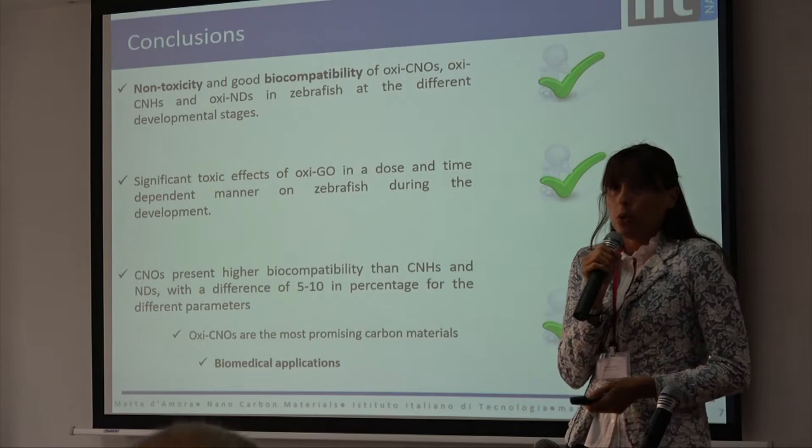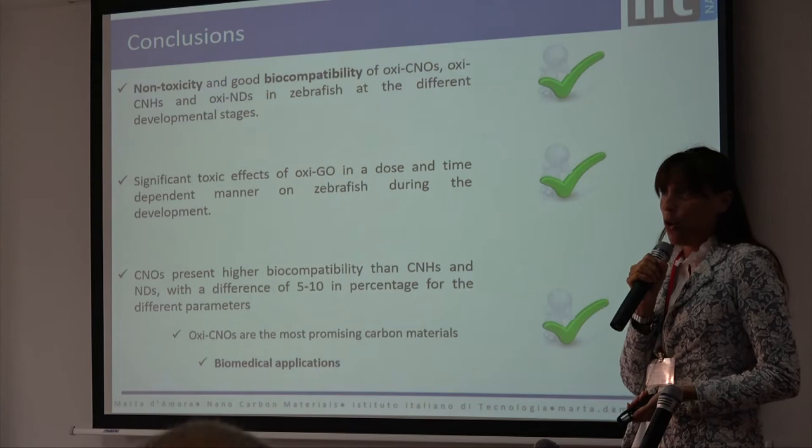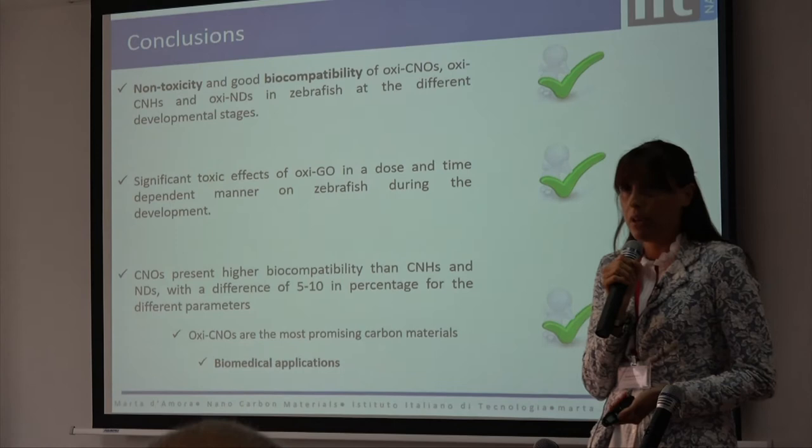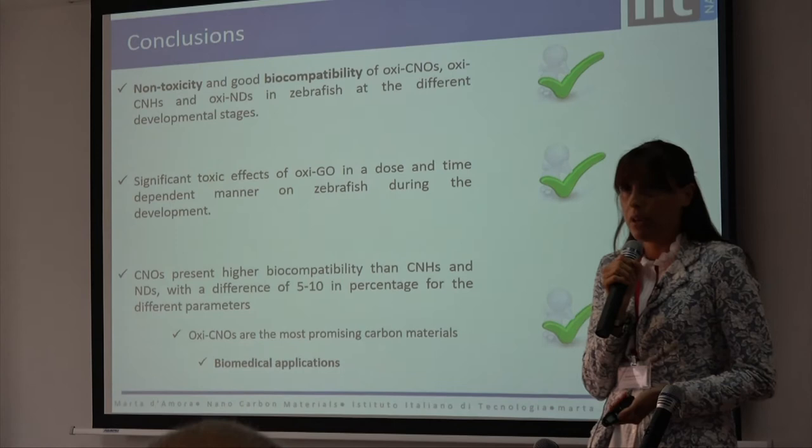Concluding, we demonstrated the non-toxicity and good biocompatibility of carbon nano-onions, carbon nanohorns, and nanodiamonds on zebrafish across the different developmental stages investigated. On the other side, we confirmed the toxicity of graphene oxide at higher concentrations. Moreover, we proved that carbon nano-onions present higher biocompatibility compared to carbon nanohorns and nanodiamonds, and we estimate that carbon nano-onions are the most promising carbon nanomaterials for biomedical applications.